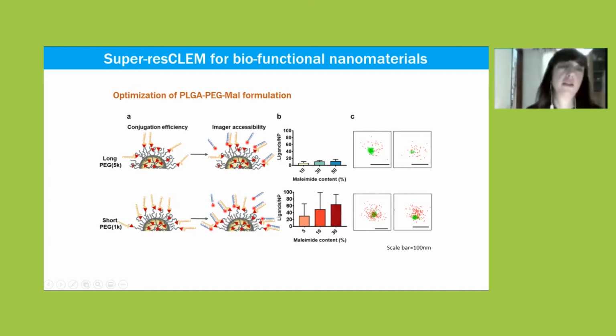So here there are brushes on the surface of the nanoparticles, and some of these brushes have ligand and some of them not, because you have a certain balance, a certain density of ligands on the surface of the nanoparticles. So what we did is to shorten the brushes that have no ligand. As you can see here, the ones that have no ligand were shortened in this new formulation, and in this way the ligand was more exposed, and then we could get a higher number of ligands.